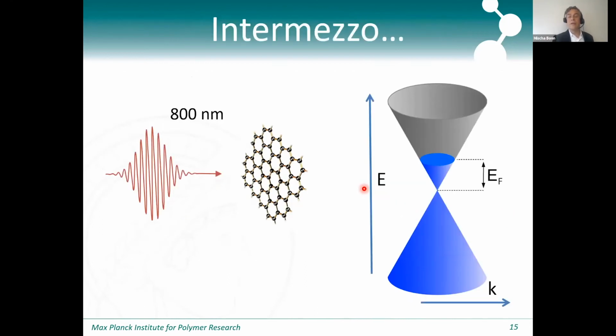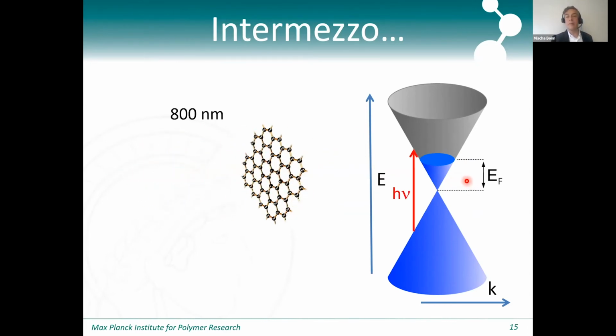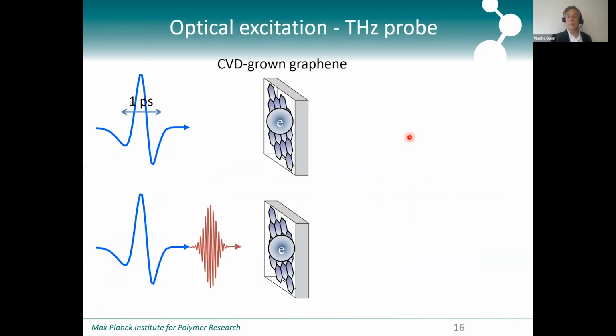So I need to take you on a small intermezzo, which is what happens when we photo-excite graphene. And so what happens to this carrier distribution, what happens to the scattering time, what happens to the plasma frequency, to the number of charge carriers when we excite graphene. And this is now a little bit of an advance, but please bear with me. And so the thing that happens, of course, is that we will transfer charge carriers from what one could arguably call the valence band into the conduction band of the material. They will scatter very quickly, and they will very quickly heat up.